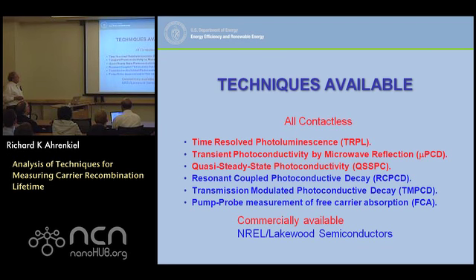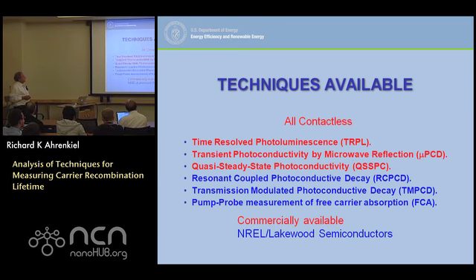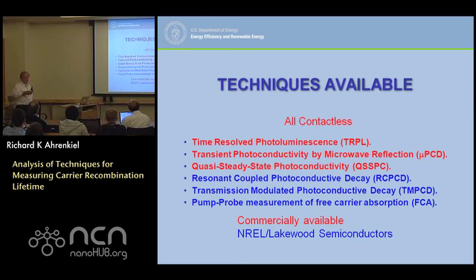Probably the other mainline technique is something called transient photoconductivity by microwave reflection, and I'll talk a bit about that. This is commercially available now. We built one of the first ones at NREL, but now you can buy it, as you guys have recently done. Then there's the quasi-steady-state photoconductivity, QSSPC, that was developed by Ron Sinton out of Stanford. I bought one of the first ones that came out. This is only useful for wafer silicon. It's not applicable to any other material.